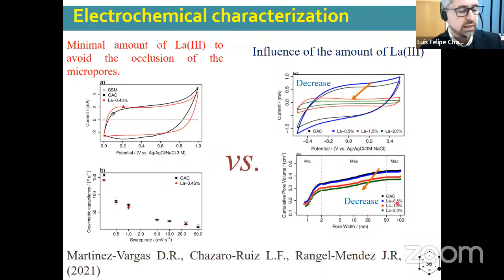So the lanthanum hydroxides can anchor, and also can agglomerate, onto the carbon surface, mainly due to their coordination with oxygenated groups such as phenolic and carboxylic groups. And then the more occluded pores, of course, decrease the polarizable surface of the carbons, which decreases their ability to retain the ions at the interface. So this corroborates that the lanthanum clusters block an important part of the polarizable area of the modified carbons, and that polarizable area was located mainly at the micropores.